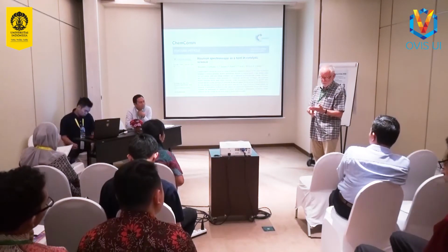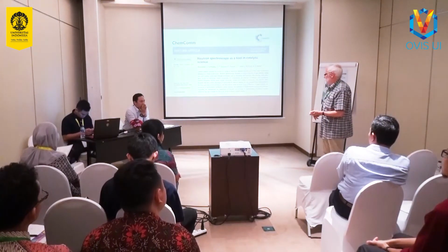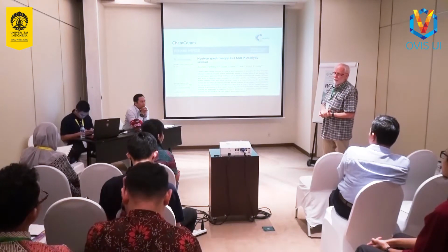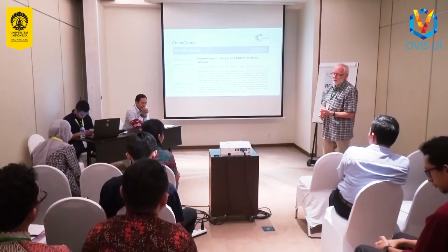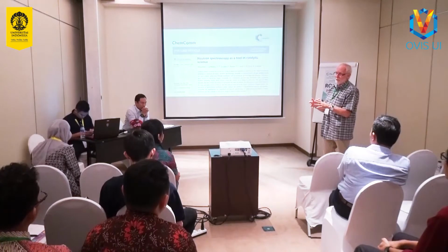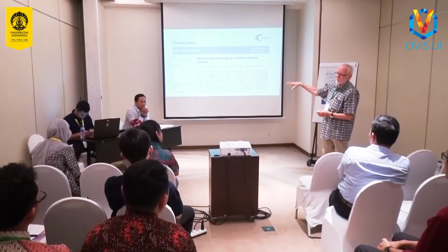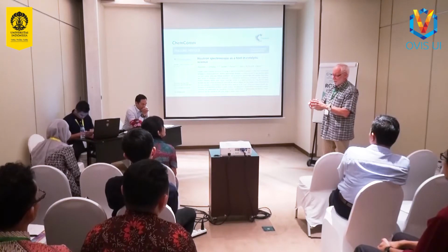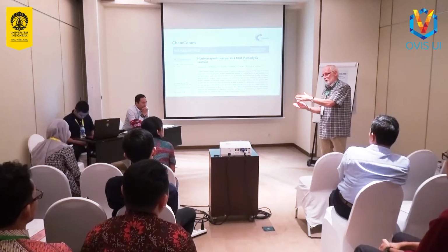But there are other processes that are more selective for making light olefins. For example, there's the methanol to olefins process, which is not Mobil's process, it's a UOP, American company. They use a smaller pore zeolite, a SAPO-34 zeolite, and that is selective to light olefins. So if your goal is to make just light olefins, you wouldn't use ZSM-5. You'd use a smaller pore zeolite, because in the smaller pore zeolite, pores are not big enough to make aromatics, so it stops at light olefins.